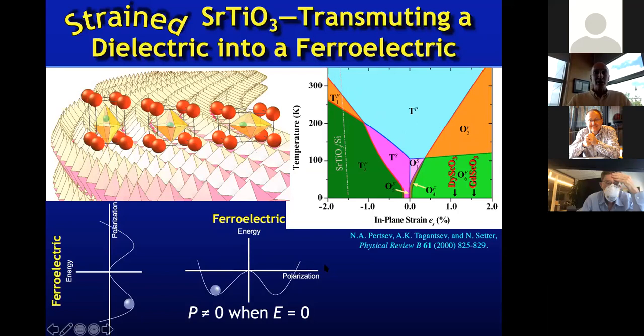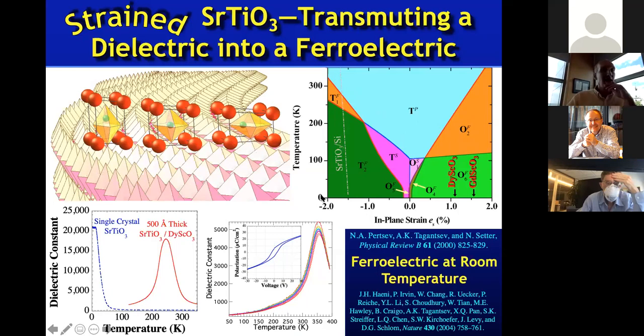And that's where experimentally we got involved in looking at what happens to strontium titanate from an experimental standpoint and putting it on top of substrates. And I'm talking about, for example, this dysprosium scandium oxide, dysprosium scandate. It's a perovskite that's about 1% larger than strontium titanate. So it corresponds, cartoon-wise, to the sketch that's over here on the right. And from this theory, we would expect that to make strontium titanate ferroelectric.